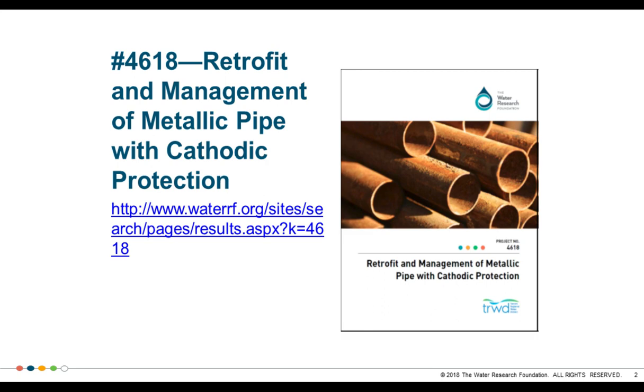In general, we've always had the view that you need to prepare for cathodic protection even if you don't apply it from day one. So for ductile iron pipe, we've always recommended that you bond the joints so that you can always put cathodic protection on it. The next step is to encase it in a polyethylene wrap. I know some people don't like polyethylene wrap with cathodic protection, but our experience has been it works. The third thing is to install test stations, and those test stations allow you to apply cathodic protection easier in the future.